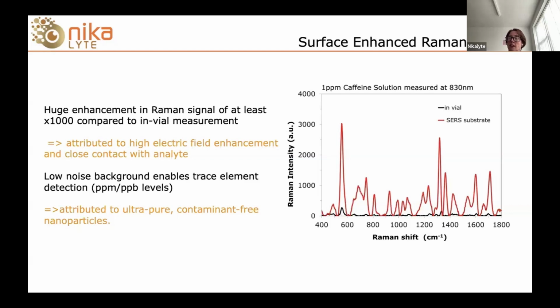So here's some data for caffeine. Caffeine is a molecule we use quite a lot in-house for testing, partly because it's quite a difficult molecule. It's not massively Raman active. So if we can see a signal from caffeine, then that shows that we have some good material. So what we've seen here with our testing is we have really good enhancement of the Raman signal compared to in vial. So the black line is just looking at a solution of 1 part per million caffeine. The red line is using our SERS substrate. So we're getting several orders of enhancement for these SERS substrates compared to standard Raman.